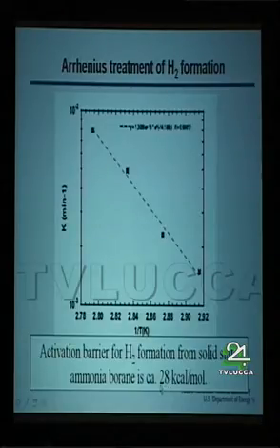This is the nucleation event, because what's important is that if you understand what this nucleation event is, you don't need a catalyst anymore. If it's a chemical process, so if the first step is rate limiting to make the first BN bond, the rest will just take off from there. Or if it's some sort of physical event, some sort of disorder you get by heating this thing up, and then it starts to lose hydrogen. If you know those sorts of things, then you can get an idea of how to enhance the kinetics.